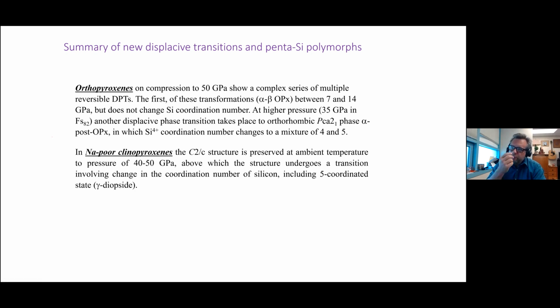In sodium-poor clinopyroxenes, the monoclinic C2/c structure is preserved at ambient temperature to pressures much higher than in orthopyroxenes, pressures of about 40 to 50 gigapascals, above which the structure undergoes a transition involving a change in the coordination number of silicon, including the 5-coordinated state that we found in gamma diopside.